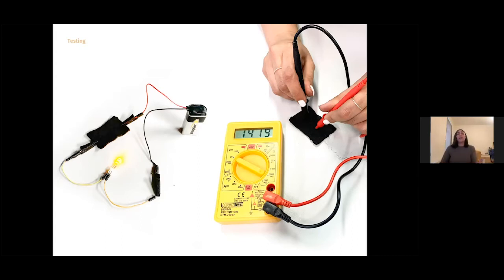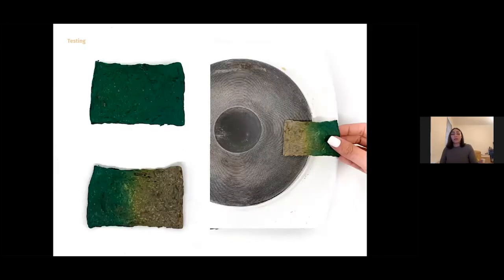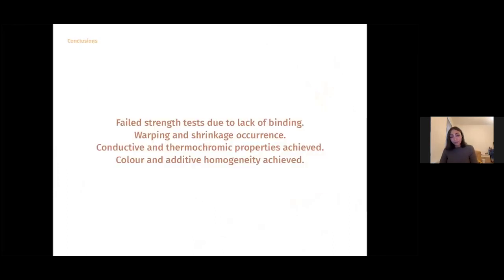As you can see here, a simple circuit was made with the one that was composited with carbon, and it is conductive, which is very promising for future developments, as well as the thermochromic one that changed color at temperatures higher than 32 degrees Celsius.